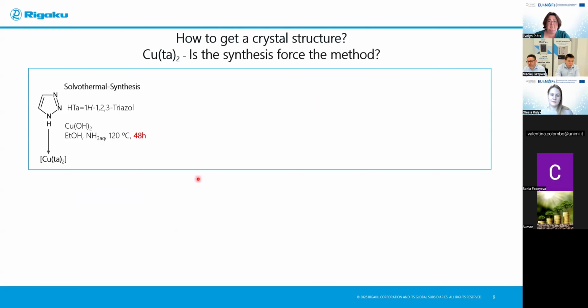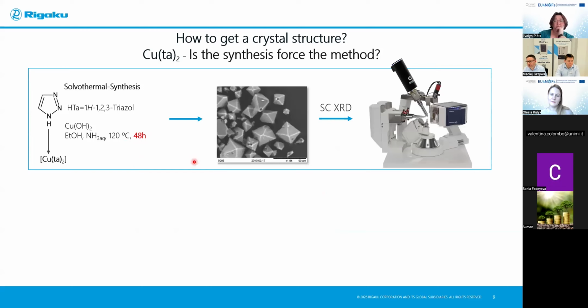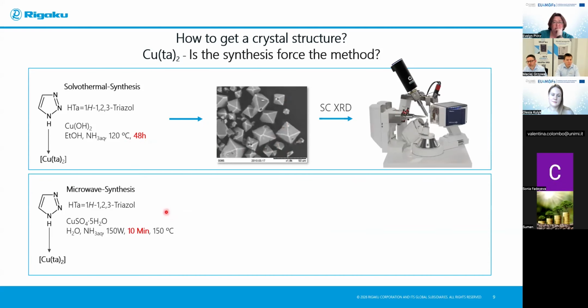The synthesis of the copper triazolate was performed under solvothermal conditions, and the reaction time was 48 hours, which results in single crystals with the maximum size of 40 micrometer, which are enabled to be measured by using single crystal diffractometer.